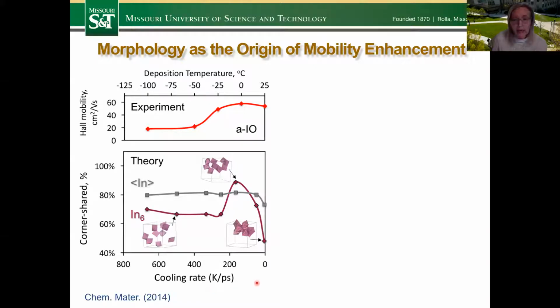And so what we find here is that when we cool the structures very fast, of course, we have a random distribution of those fully coordinated indium-6 atoms, as expected for the truly amorphous phase. When we cool them very slowly, and here slow is about 5 Kelvin per picosecond, then we start seeing clustering of those 6 coordinated atoms, which is actually the initial step for nucleation of those nanocrystallites that we see in the experiment. But at intermediate cooling rates, about 200 Kelvin per picosecond, we have chain formation. Long chains of these fully coordinated atoms actually help to develop conductivity chains in these materials, and we believe this indeed explains the mobility peak in this material.